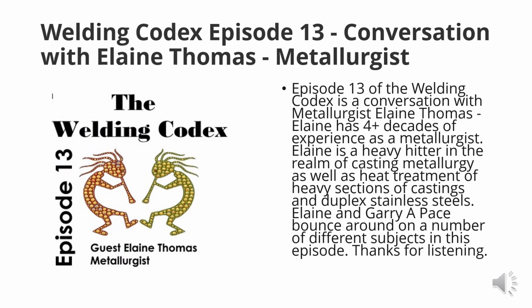In my professional universe, you're always harping on welders: preheat this, preheat this, preheat this. With the carbon steel materials, say a high strength carbon steel or something with a little more carbon in it, and then you switch over and they're welding on duplex stainless steel, and you're like, whoa, whoa, whoa. Dude, that thing is more than 200 or 300 degrees. Why are you striking an arc on it? Just sit there and don't touch anything until that thing is under a couple hundred degrees.